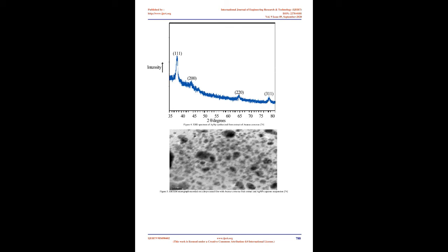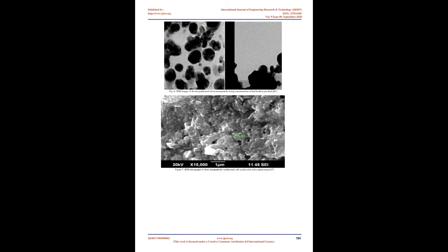They suggested experimentally that concentration of aniline does not have appreciable effect on the shape, size, and the size distribution of AgNPs. The most frequently used reducing agents among various ones are sodium borohydride, citrate, ascorbate, and compounds containing hydroxyl or carbonyl groups like alcohol, aldehydes, carbohydrates, and their derivatives 65. During preparation of nanoparticles, it is paramount to use protective or stabilizing or capping agent which will stabilize dispersed AgNPs in order to prevent agglomeration.